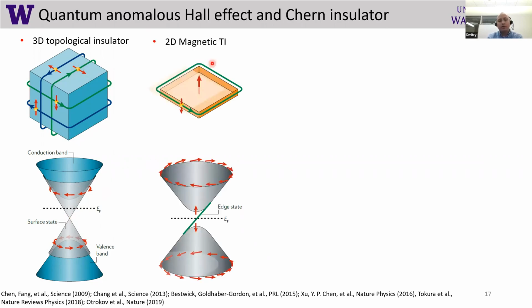Now if we take a two-dimensional material, so essentially we make the topological insulator very thin, and then somehow manage to introduce magnetism very carefully, we will end up with the following situation. First, our bulk will be insulating, and instead of a gapless surface state, we would now have a gapped state. Magnetism essentially opens a gap on the top and bottom surface of this 2D sheet. And now the only conducting entity here will be an edge state. This edge state would run on the perimeter and have exactly the same properties as the quantum Hall edge states